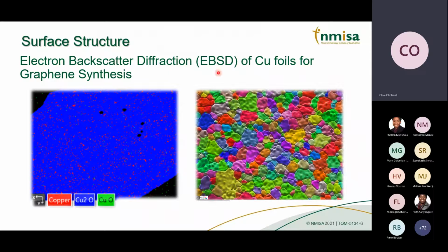Electron backscatter diffraction, or EBSD, of the same copper foils confirms the presence of these copper oxides with some copper shining through. So this oxide can be further reduced using hydrogen treatment to get to this. This is an EBSD image of those crystals. It's a highly magnified image.